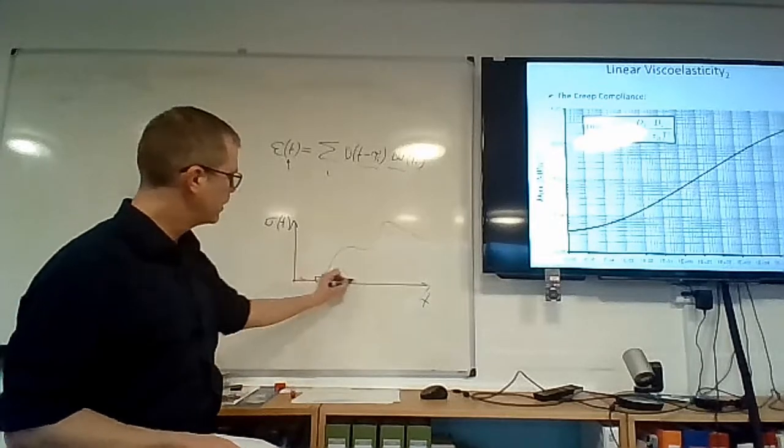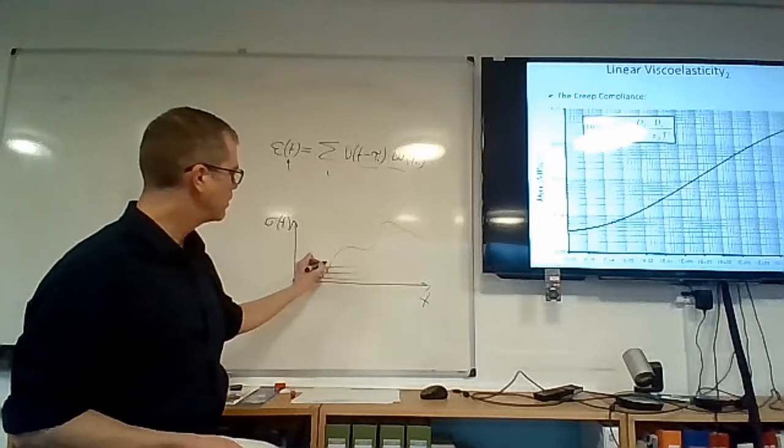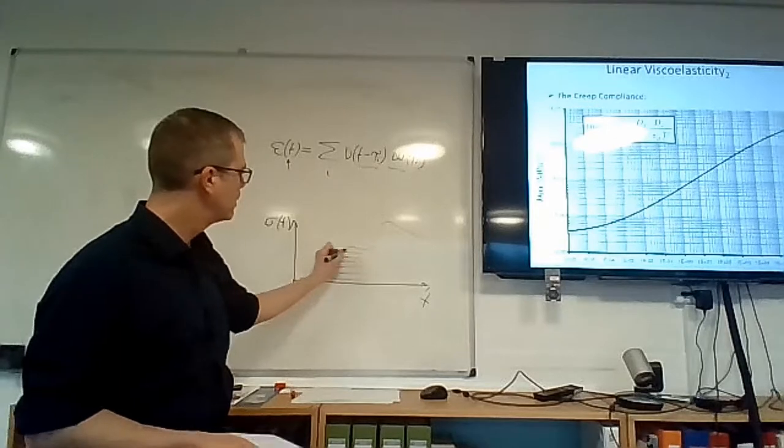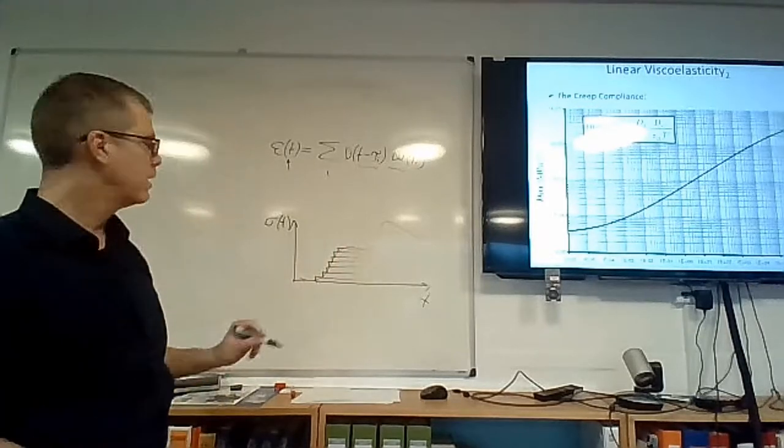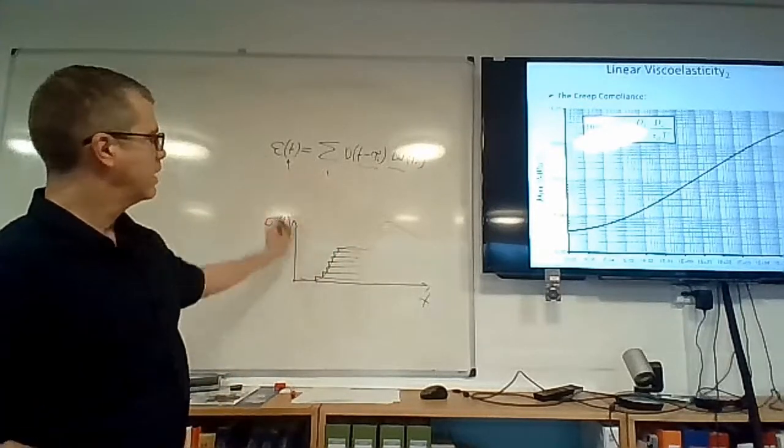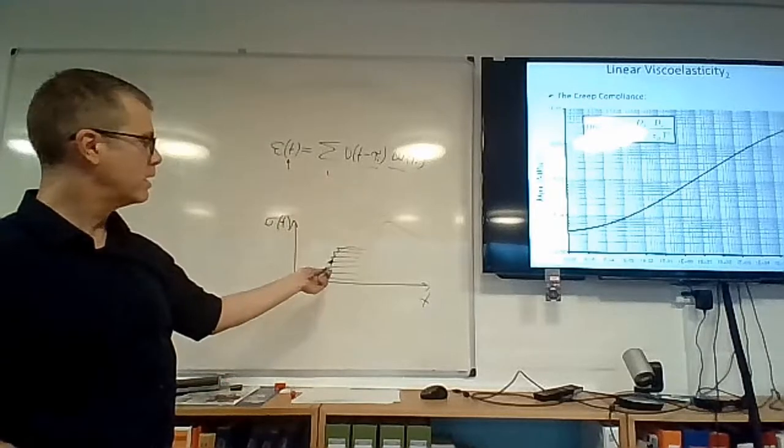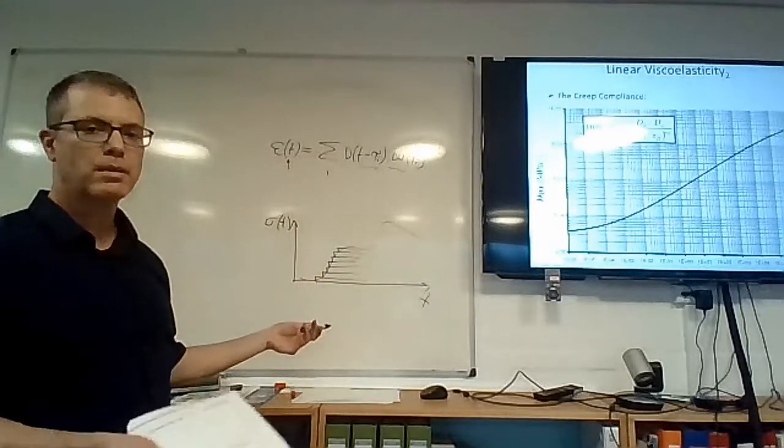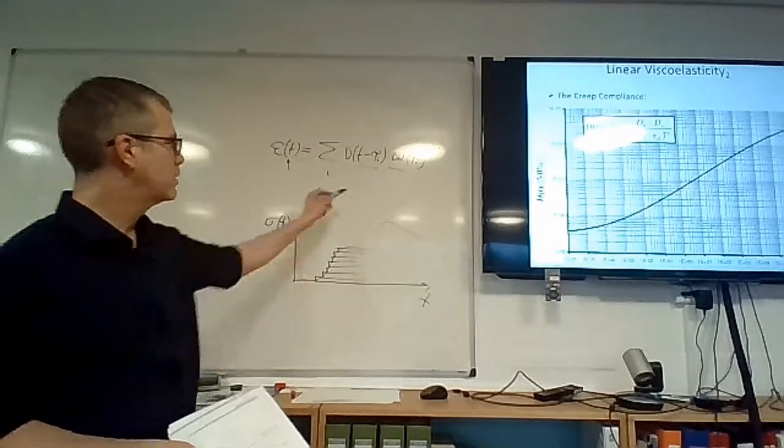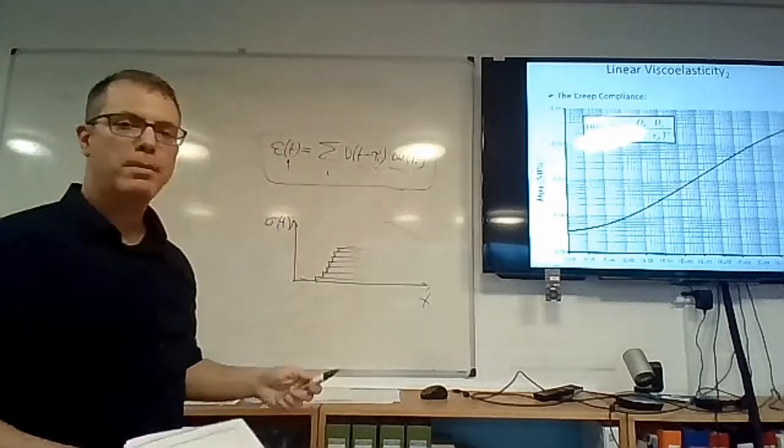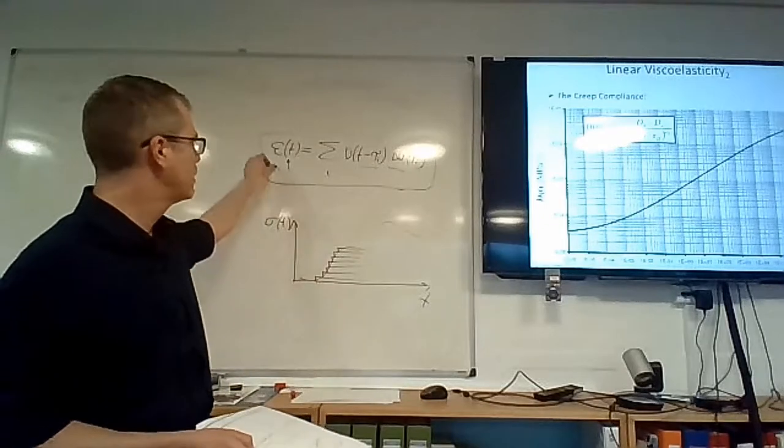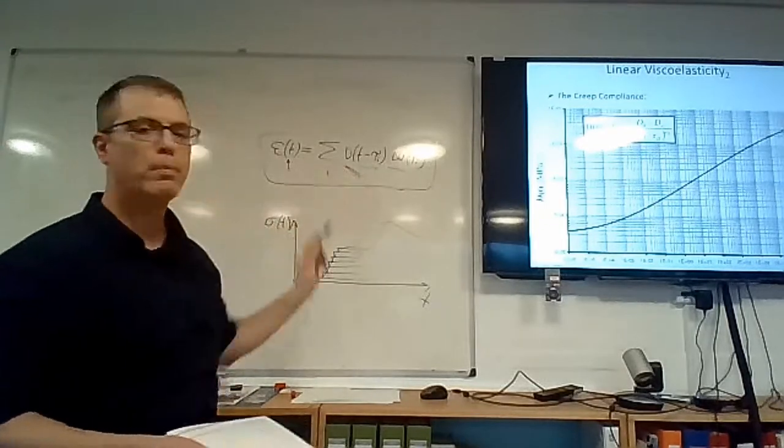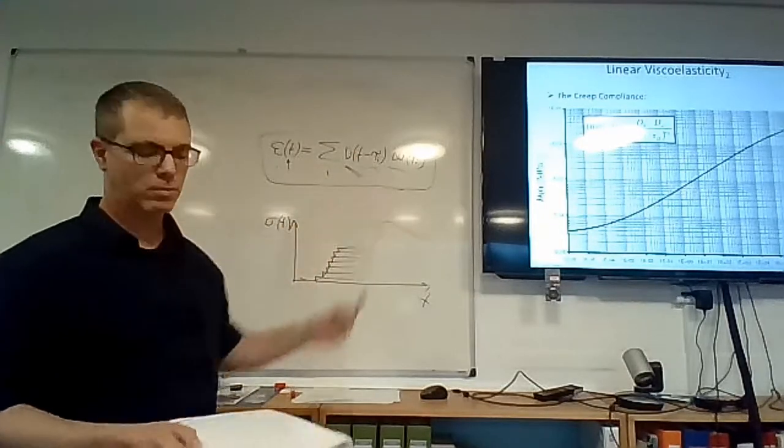So what we need to do is split this into little stress steps. And since we have the ability to analyze the strain due to any number of stress steps, this stress history can be approximated as best as we want. And that means that with this formula, you have the ability to solve for the strain in a viscoelastic material, given that the creep compliance is known for any stress history of interest.